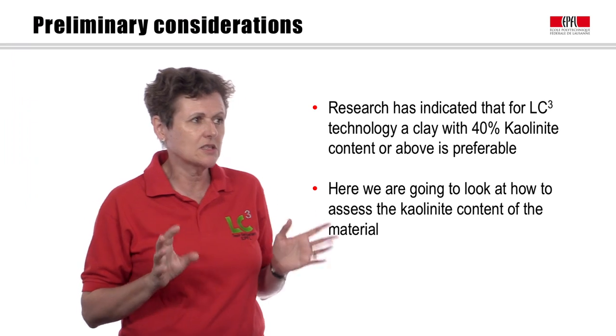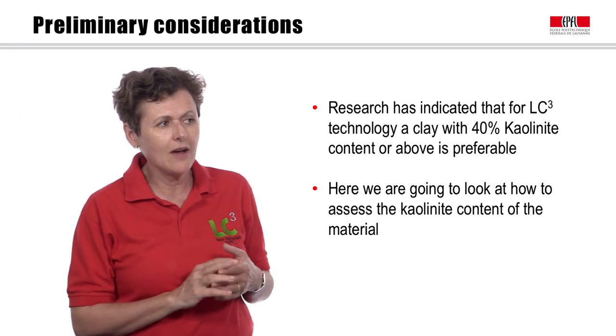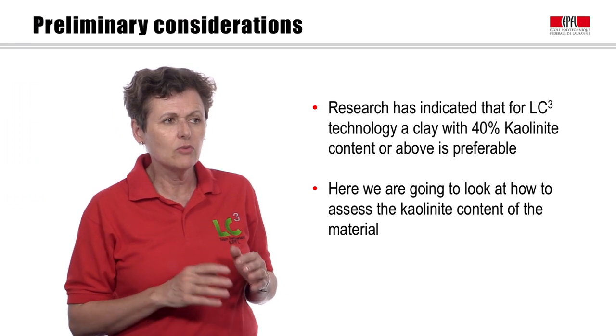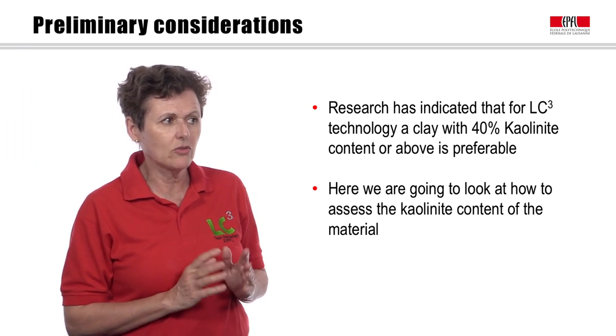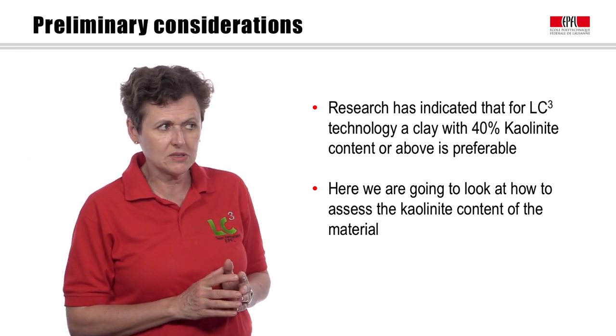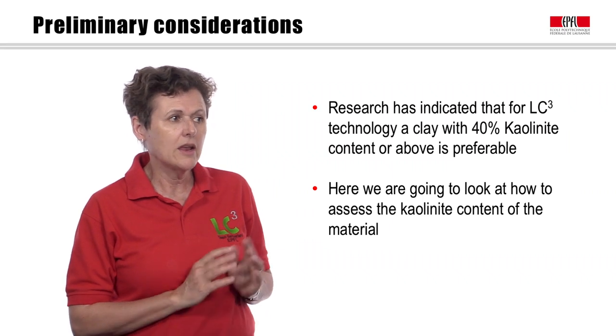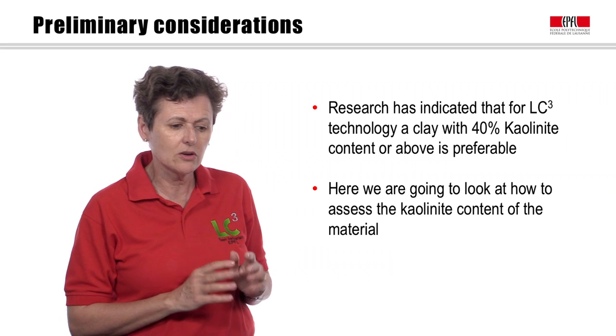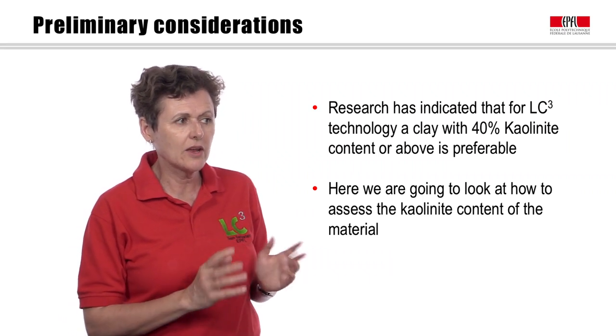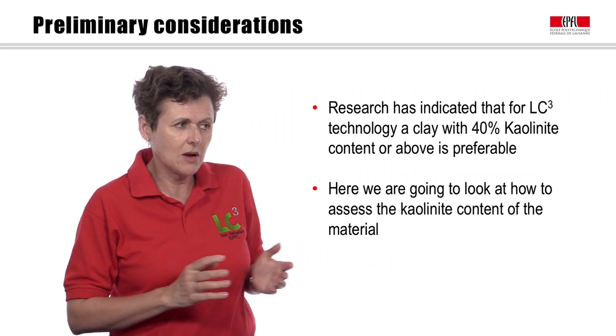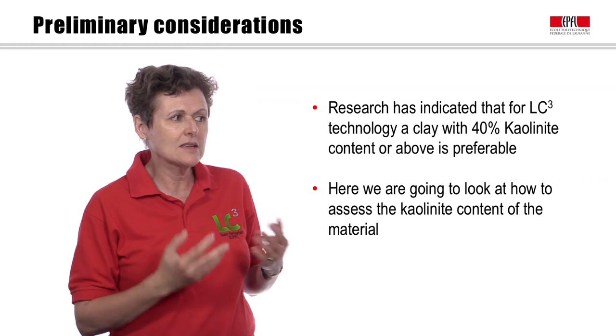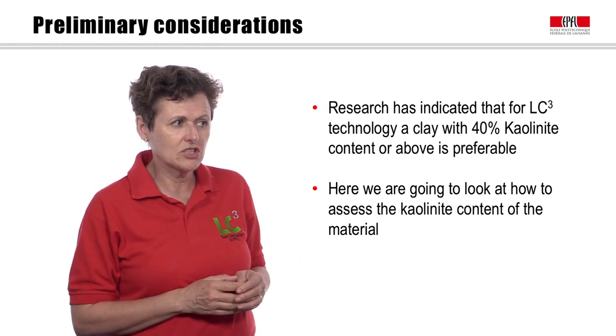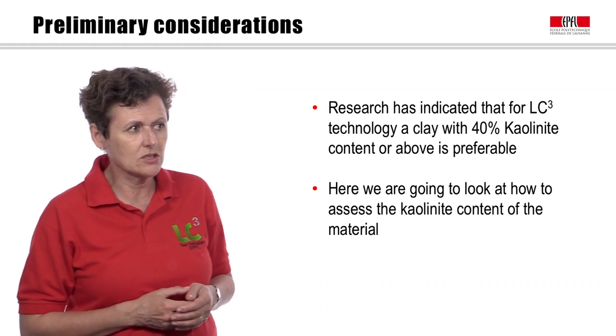Our research has shown that to have a clay suitable for the LC3 technology you really need to have a kaolinite content of about 40% or above. We're going to look at how you can measure that kaolinite content, including very simple methods that can be used by almost anybody, and then how you take all that information together to see if your clay is suitable.